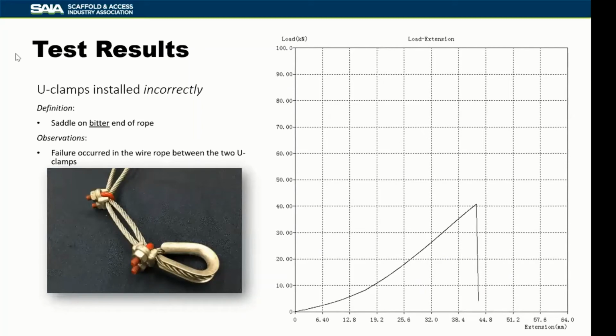If we look at incorrectly installed U-clamps, with the saddle on the bitter end rather than on the live end of the rope, you can see that the failure occurred between the 2 U-clamps. Our force to fail was significantly less than what we'd seen in the other instances. The elongation wasn't as high, but the failure did occur between the 2 of them at a significantly lower load.